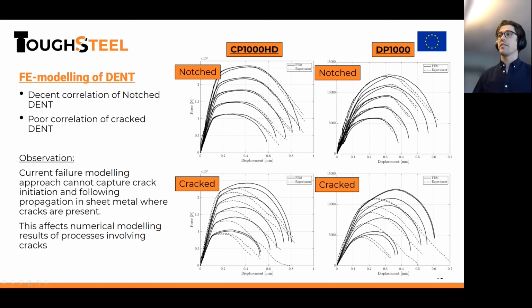And the observation from this is that if you try to model processes involving cracks and crack propagation in high-strength steel with a GISSMO model, you might run into a problem. In this case, it seems like you need a different approach to deal with the crack tip stress, crack tip failure and the propagation. The failure locus that we calibrated doesn't really include this stress state. And I guess you can see how this can be an issue. If you imagine having a forming simulation using this GISSMO model, where you have an edge that is being stretched, and if this edge in real life has a crack, I'm quite sure that you will have quite bad correlation between your model and reality.